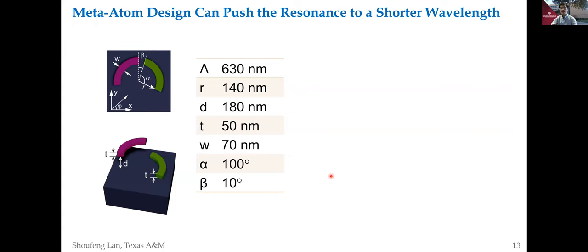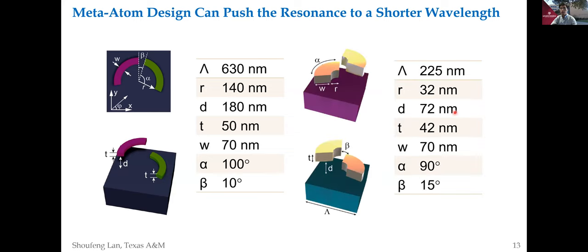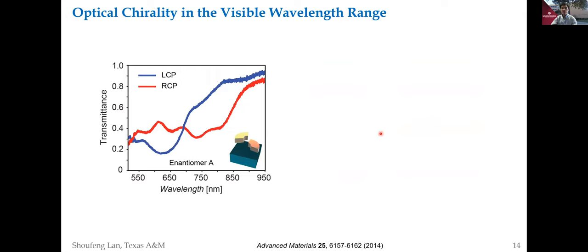So if you want to design a shorter resonant wavelength, from the infrared to visible, we can simply use the following geometry by shrinking the first three geometries. Indeed, we observe the giant chirality in the visible range. For example, at the wavelength of around 600 nanometers, we observe the transmission difference between RCP, that is the red curve, and the LCP, that is the blue curve. The difference is around a positive 0.3 over here.